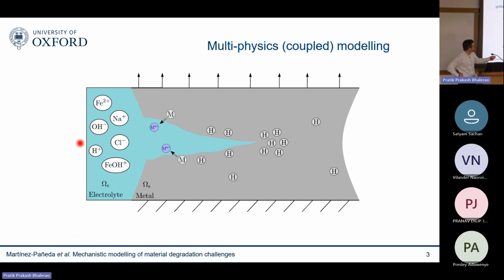Then lots of things are happening as well at the surface, in the interface between the metal and the electrolyte. You have reactions due to corrosion. You're losing metal atoms. You have reactions that bring hydrogen atoms inside of your metal. Those hydrogen atoms move around within the metal, within the crystal lattice, driven by gradients of hydrostatic stress, so coupled with the mechanics. They embrittle the material at multiple scales.